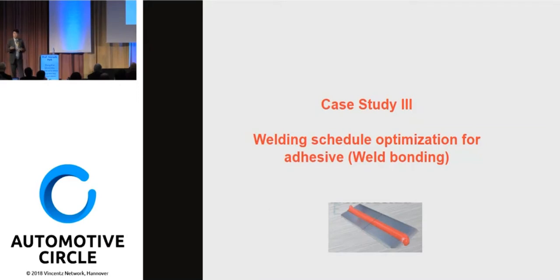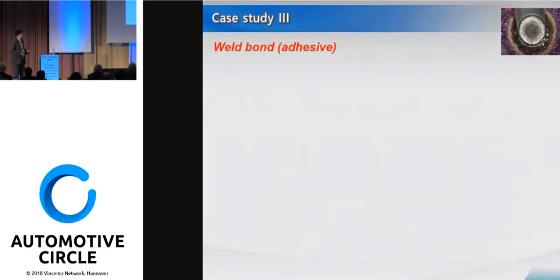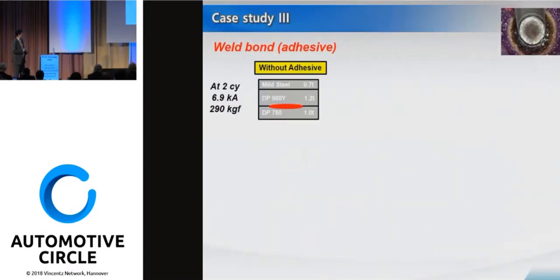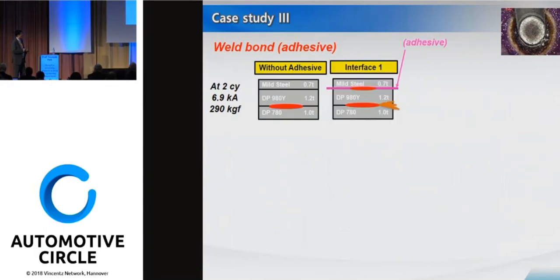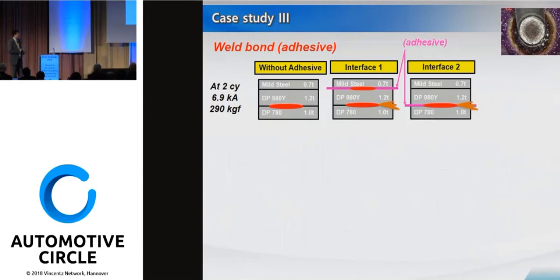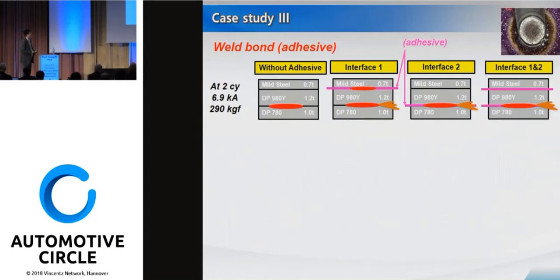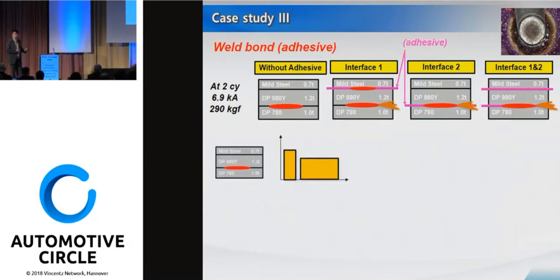OEMs use a lot of adhesive nowadays for crashworthiness. Here's what we have. In the case without adhesive, you have heat generation here early. In the case of adhesive at interface 1 on the mild steel side, the adhesive actually works as a heat generation source, so you probably don't need a pre-pulse, but there's a splash on the high strength side. And if you have adhesive on the high strength side, interface 2, you will have very excessive spatter here. In the case of interface 1 and 2, same thing. So this is what I proposed, pre-pulses.